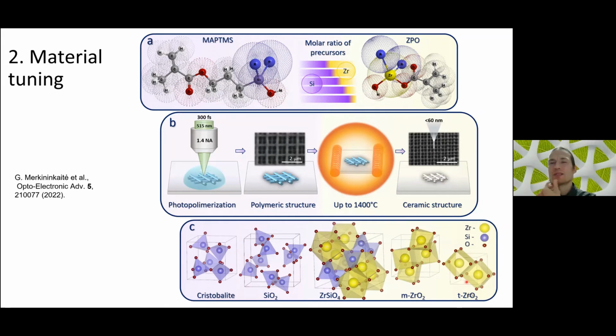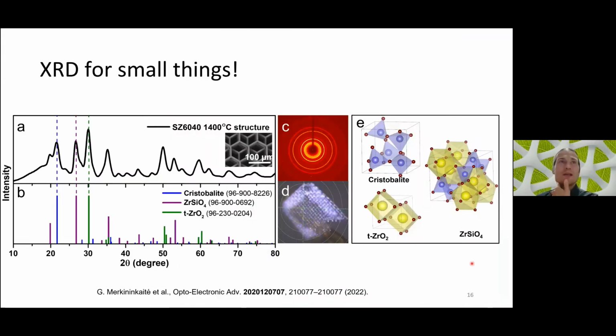inorganic crystalline phases. So this was quite novel, to apply XRD for small things, and it showed that the higher the content of either zirconium or silicon we have initially, the higher the output or throughput of its conversion we get, finally forming either more cristobalite or tetragonal zirconia materials, depending on the needed applications.